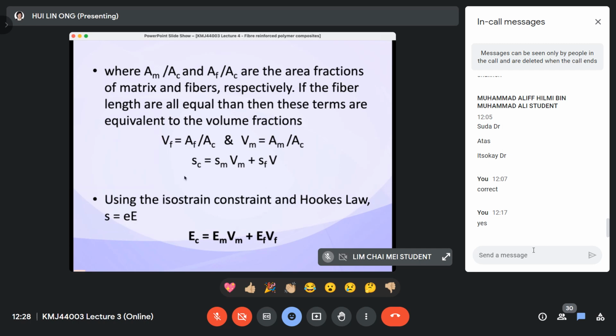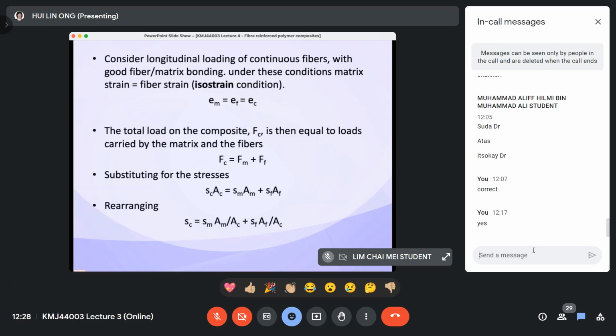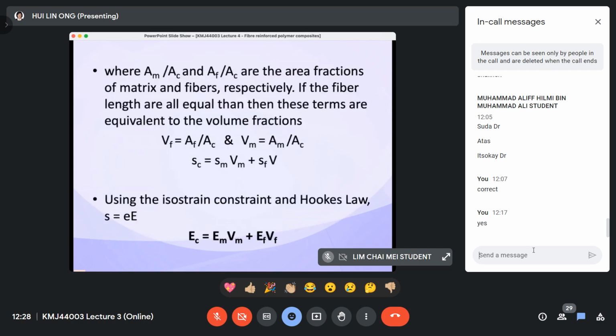So when the force is applied in the same direction as the fiber arrangement, then it is isostrain. So from there, you can slowly derive the equation. It's not a long derivation. These are all worth marks. So then you come to this equation. For this, we can predict not only the modulus of the composite, but also the yield strength, the tensile strength, and also the density of the composite. We can predict four things in this equation. We call it the rule of mixture.